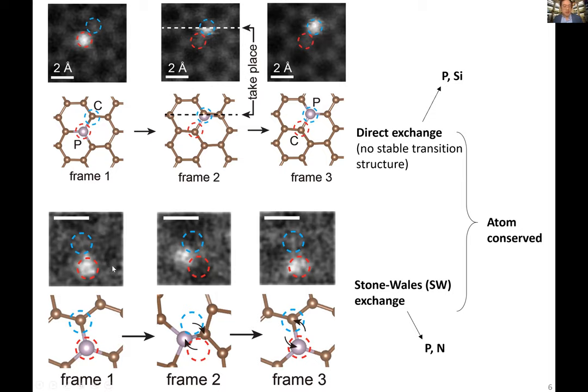And sometimes we also see a 90 degree rotation. Actually, this is a very famous transformation in graphene, where you rotate this bond by 90 degrees and you create two heptagons and two pentagons out of four originally near hexagons. So that's called a Stone-Wales defect, a Stone-Wales transformation. And depending on the angle of the sample with respect to the beam, we can either get clockwise or counterclockwise 90 degree rotation. And this can also be done for nitrogen atoms.